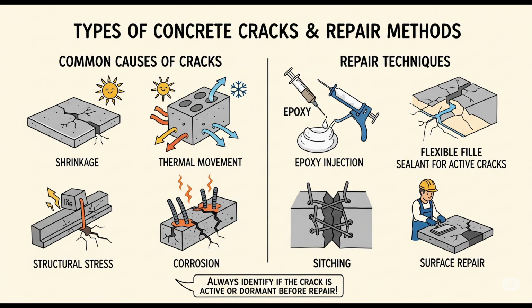Our source paper, Dr. Melham's work, concludes with some really key recommendations for preventing and managing cracks in the first place. First, it stresses implementing all necessary design measures and precautions to minimize cracks right from the start, always considering the specific nature of the loads the structure will face. Second, simply using good quality concrete is essential. The paper mentions not less than C20 grade as a typical minimum, referring to its compressive strength. Third, ensuring sufficient concrete cover for the rebar is critical for protection, remembering those minimums, like 2.0 centimeters for beam columns, 2.5 centimeters for exposed slabs, and never less than the rebar diameter itself.